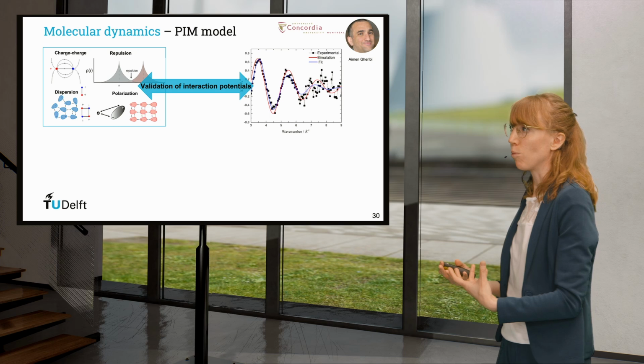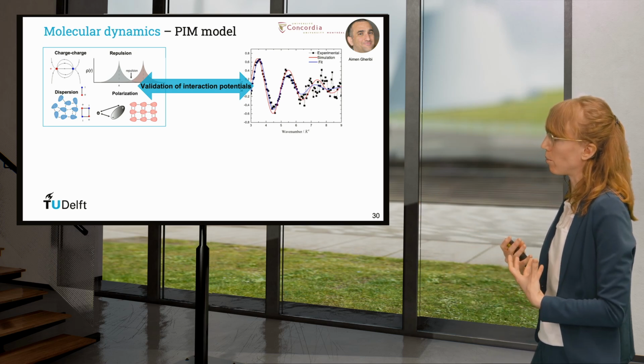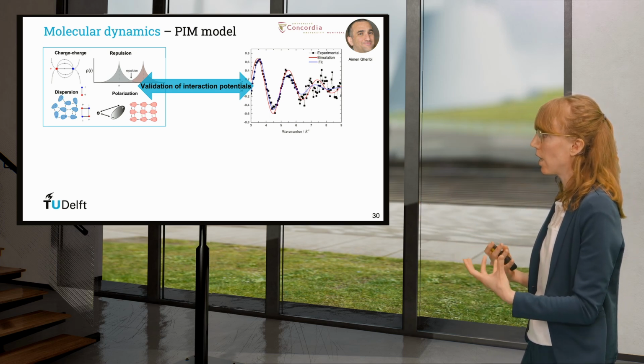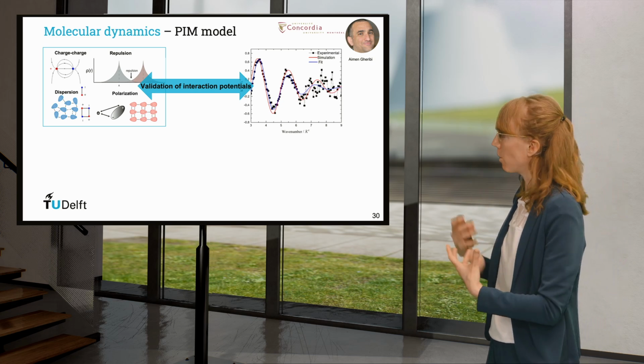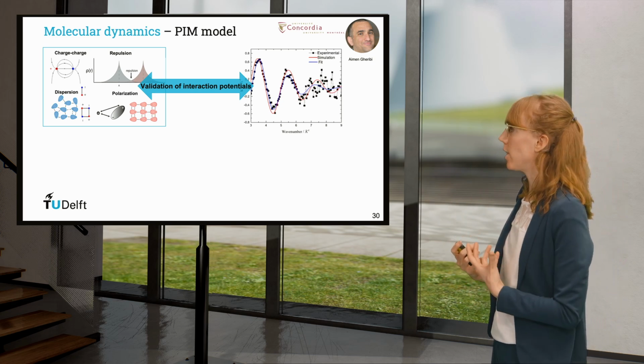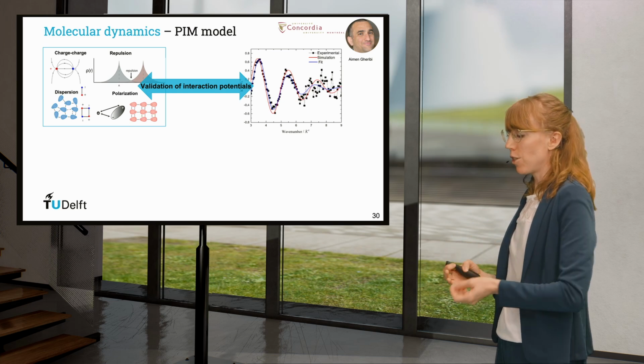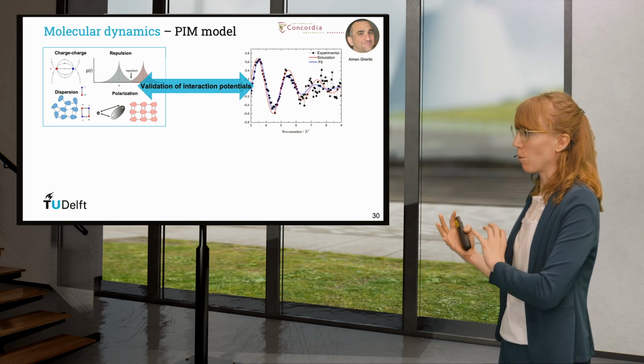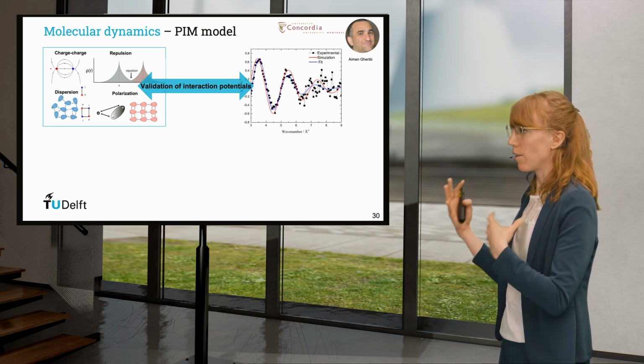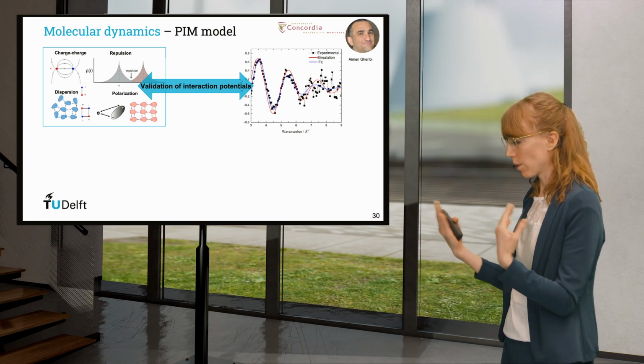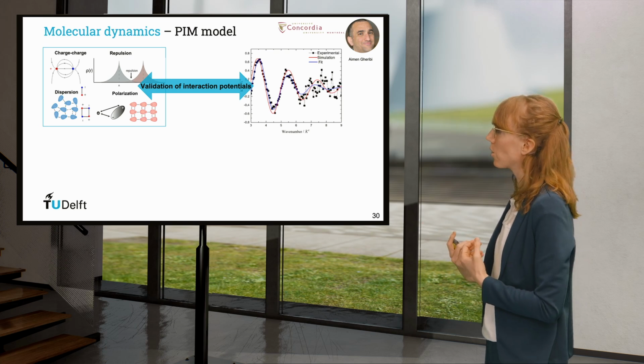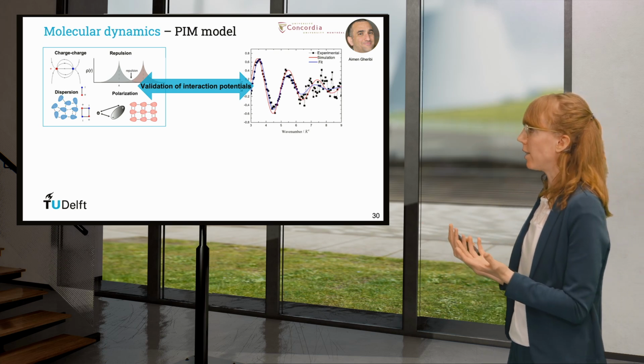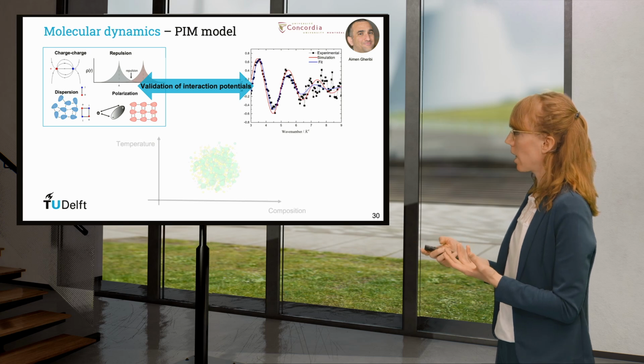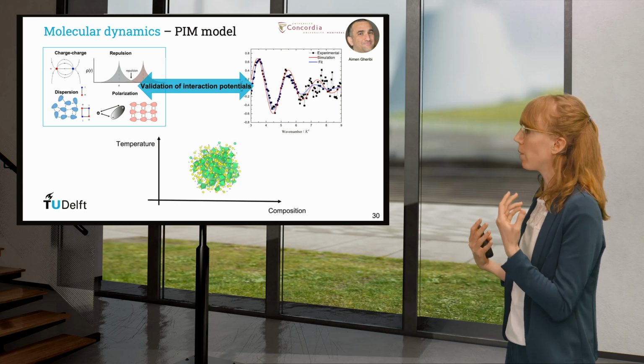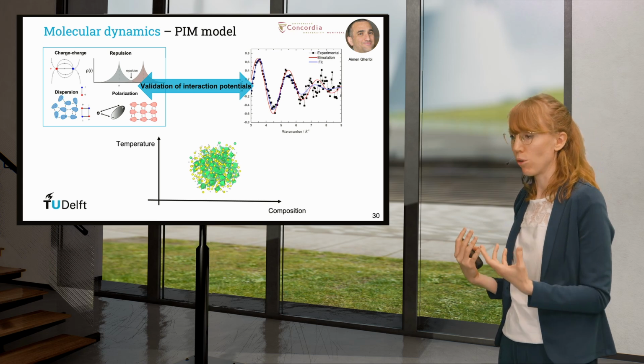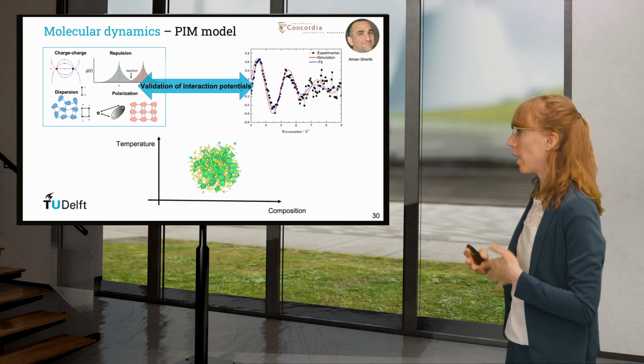But if we want to have even more information, we need to combine the experiments with some molecular dynamics simulations. And we do that in collaboration with someone from Concordia University in Canada. With these simulations, we can simulate our EXAFS data. And if the match is good, and we can work to make sure the match is good, we have been validating the interaction potentials. And once we have this validation, we know we can get a detailed picture of the local structure at any temperature and any composition.